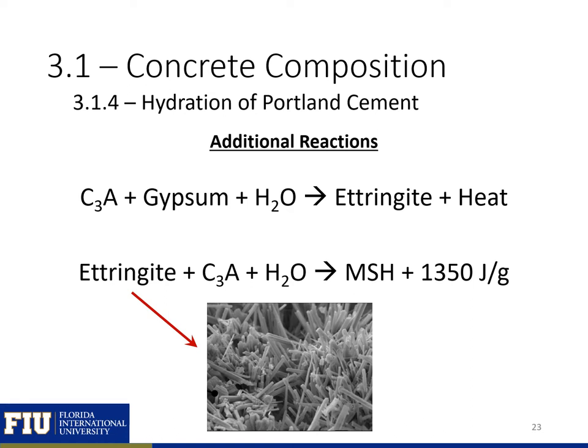However, a high early heat will prevent this reaction from occurring until much later. In this scenario, there's no room for the ettringite to form, so the formation of ettringite causes cracking. This durability issue is called delayed ettringite formation, or DEF. Note that the presence of ettringite in the concrete matrix does not mean there is DEF, as ettringite is always a product of hydration. DEF is only a concern if the ettringite forms after final set of the concrete.